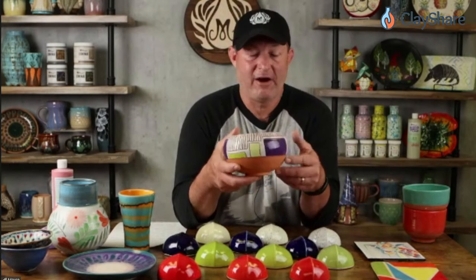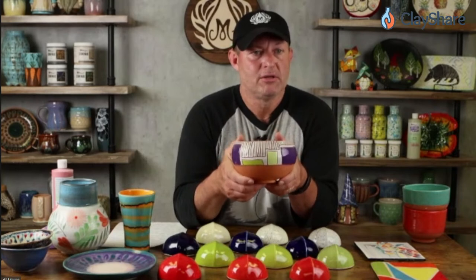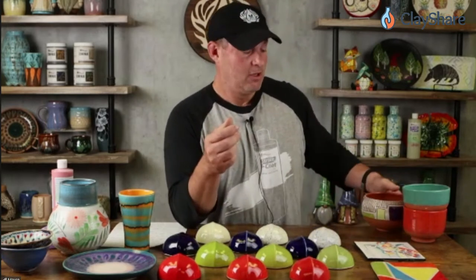You can also apply stroke and coat on wet clay — thrown on the wheel — just like a slip, and do a once-fire. People save money and time by only firing once: they apply the stroke and coat on greenware wet, let it dry, skip the bisque fire, and fire all in one go up to cone 06 or cone 6. Here's an example of stroke and coat done in sgraffito — applied wet when thrown, then carved away. Different colors can be layered over each other, yes.